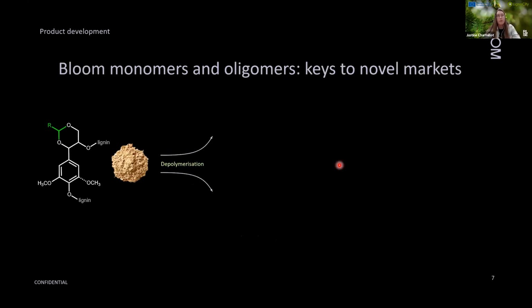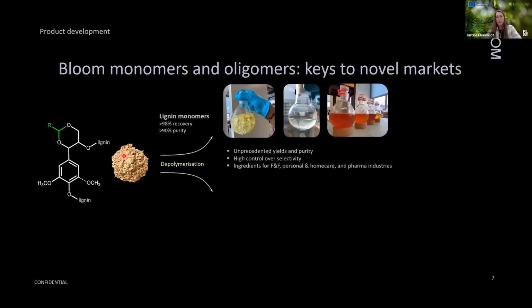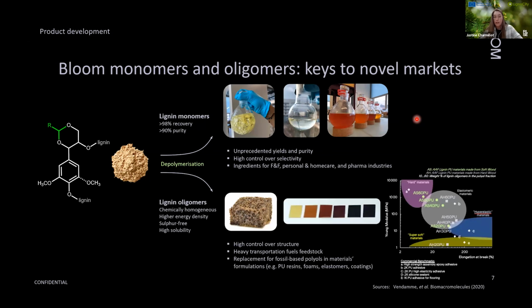There's something else that we can do with this lignin. It's, of course, depolymerize it. So when we do that, we obtain two different things. The first one is, of course, the monomers. So we achieve a high purity and a good yield. We have good control over the selectivity. We can choose specifically what type of monomers we want. And basically those monomers are phenolic compounds. And those are valuable molecules that can be integrated in food and fragrance, cosmetics, pharma industries, chemical building blocks, and so on. And the second stream that we have out of this depolymerization is the lignin oligomers.